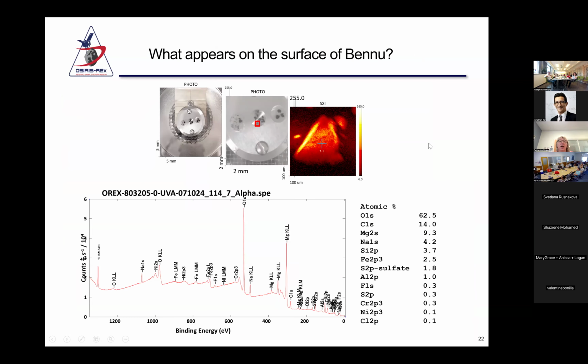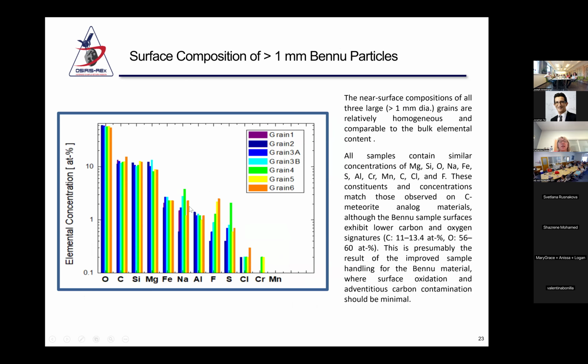So what do we see? On the surface of these particles, we see generally similar elemental concentrations to what they see in the bulk, but not exactly. We see high concentrations of oxygen from the silicates, the carbonates, the phosphates, etc. Some carbon, silicon, and a fair amount of sulfur in both sulfides and sulfates. We're doing this analysis for all of the grains so that we can see the homogeneity or heterogeneity of the material. You can see our findings here.